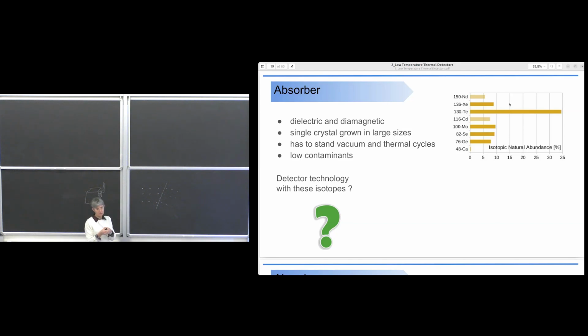The problem is that you cannot grow these diodes in large crystals, and so if I remember well, the size of this detector was a cubic centimeter, so you need an array. I mean, to go to 1 ton, you understand that it's a bit difficult. And in any case, the energy resolution was not so good.